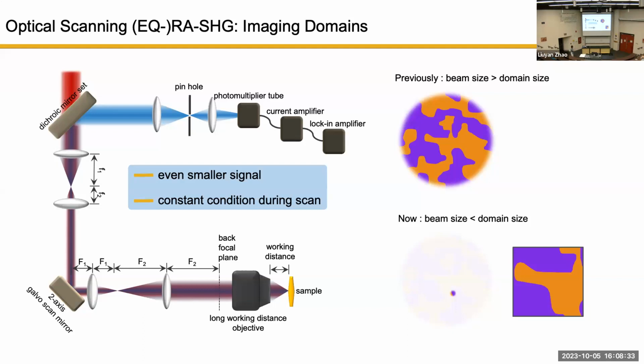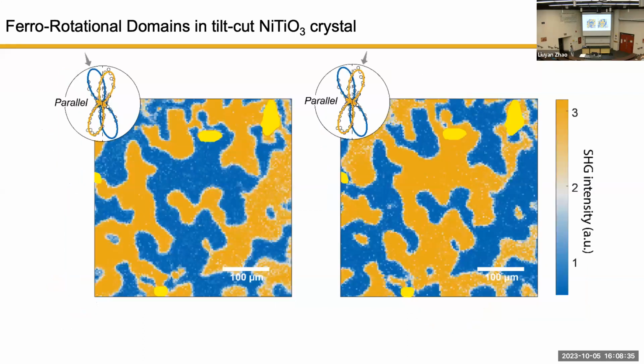So we made this effort. After doing so, you can now see the domain map of the ferrorotational order. The blue and the yellow represent the two opposite rotating cases, and these two maps just highlight one versus the other. So by improving the sensitivity, we finally can see the domain distribution.